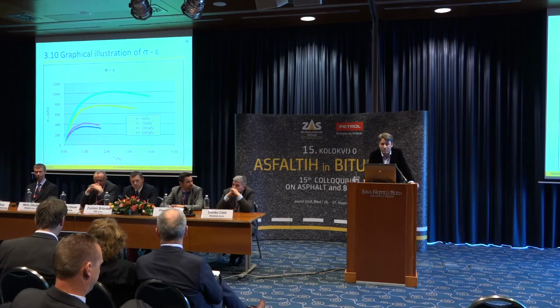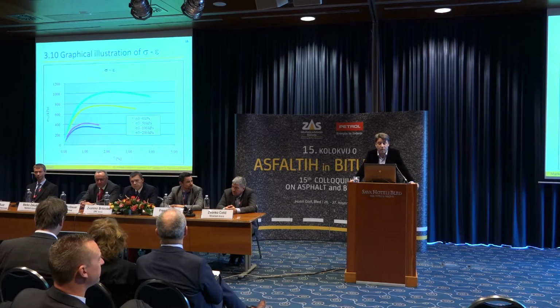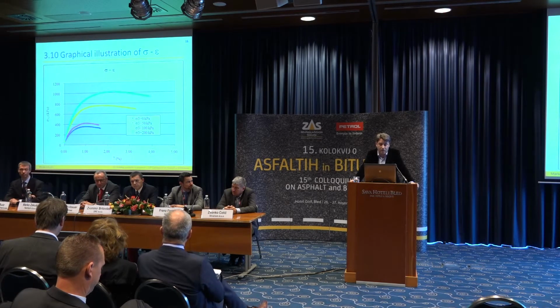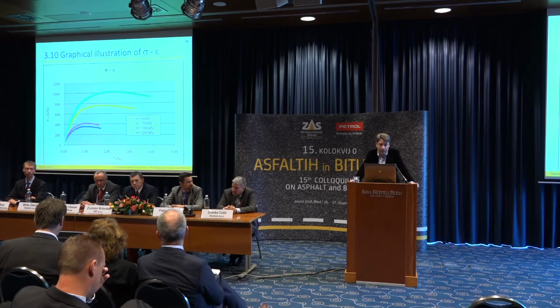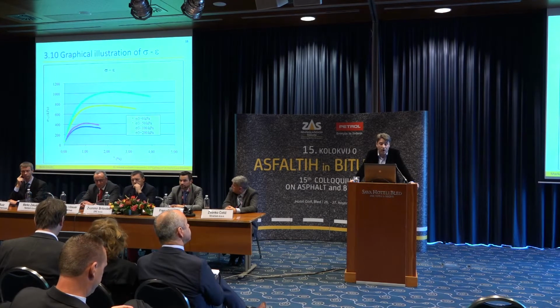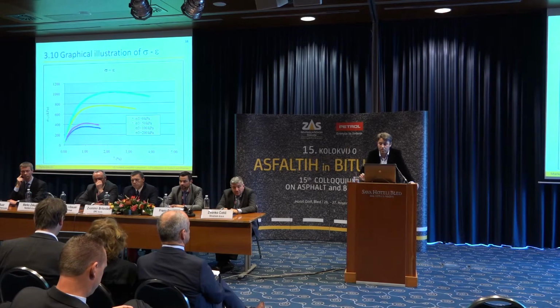This slide shows the compression stress and strain. Actually, stress is on the vertical axis, and strain is on the horizontal. The blue line is the one without sigma 3, not laterally pressed, and each consecutive one is pressed with 50 kilopascals, 100 and 200.